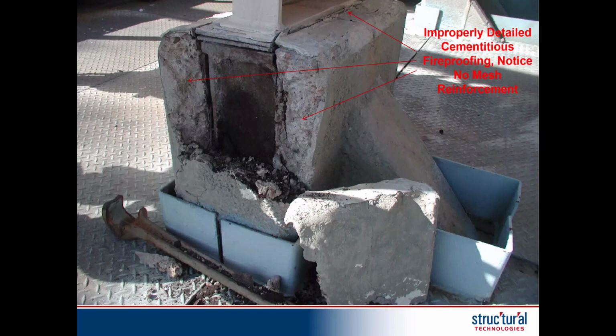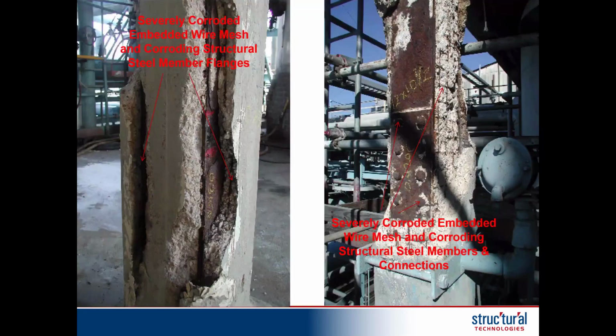They really didn't understand the root cause, especially as it relates to failure of the fireproofing. We also see that there can be many things that are embedded within the concrete that are critical for corrosion. The photo to the right is showing riveted connections. This very old structure was built back in the 1920s. This is in the Gulf Coast, but you can still see some of the remnants of the embedded mesh there.